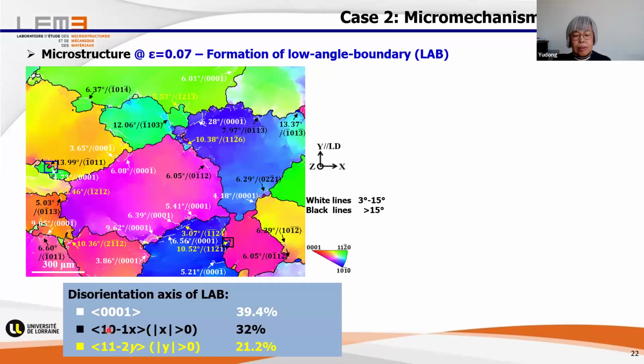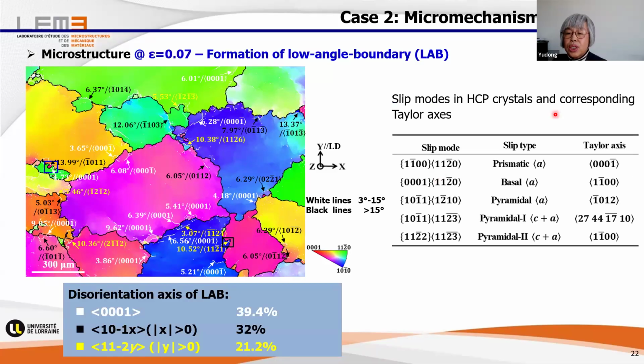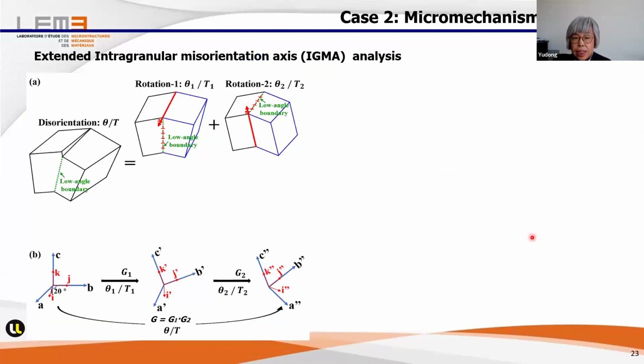And then what is behind the formation of such an axis? We made a comparison with the other slip modes, and we see there is no fit. That means it is not realized by the possible activation of the other slips. And so we have to enlarge our search scope a little bit, and so we extended this wonderful method.